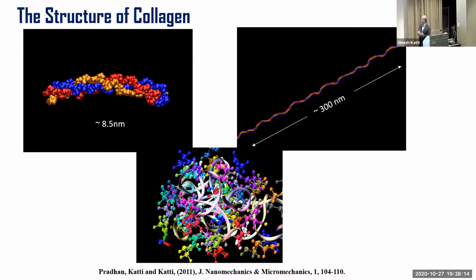While we were studying the bone, we were intrigued by this collagen, which is one of the two components of the bone. And collagen also happens to be the most abundant protein in the human body. Now, at that time, when we started investigating, all the literature, all the work that was being done was on the short 8.5 nanometer long collagen molecule, a representative collagen molecule segment. In fact, the actual collagen molecule in the bone is 300 nanometers long. And so what we decided to do was to build a full-length collagen molecule and do molecular dynamics simulation. It's extremely expensive. We need high-performance computers, supercomputers, to be able to do that. But we were able to do that.